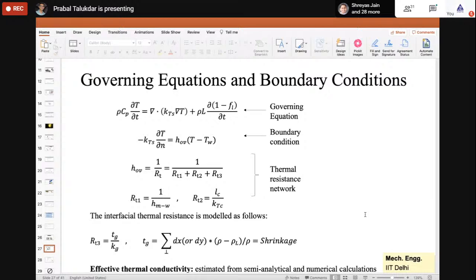So you don't need experimental measurement of temperature all the time. From one measurement of temperature data, you will be able to predict this Kg, and then you can do it for any kind of casting speed and for other different parameters.